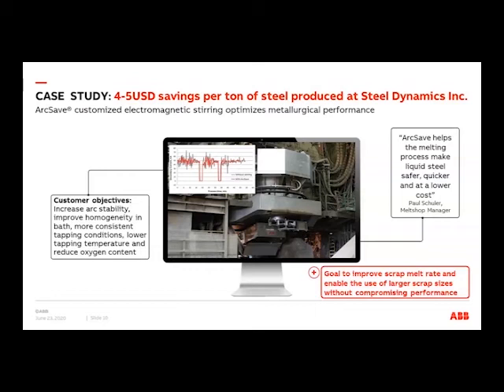They were using 100% scrap with a daily production rate of 22 heats per day. The tap-to-tap time was 65 minutes, producing 600,000 tons of carbon steel annually. The customer objectives in this case were to increase the arc stability during the melting and improve the temperature and chemical homogeneity in the liquid bath. They wanted more consistent tapping conditions to the next process step, lower tapping temperature, and reduced oxygen content.